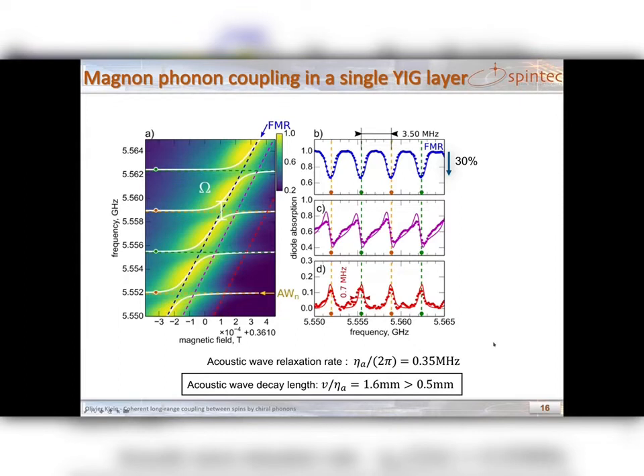Here we look more closely at the spectrum. If we take a look at what's going on along the blue line, we can see nice dips at every phonon frequency. These dips are due to the magnon-phonon coupling, and they also increase the line width, and this creates a decrease of the amplitude. If we go away from the Kittel mode, it becomes a dispersive or Fano resonance. Far away from it, it becomes a peak as expected from the theory.